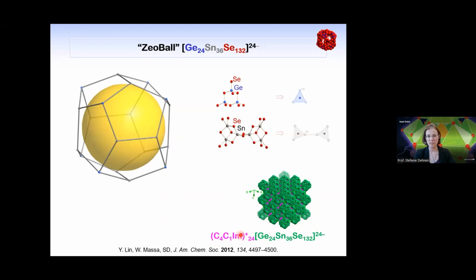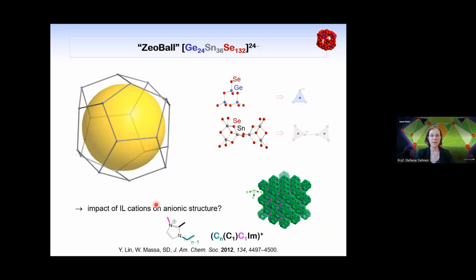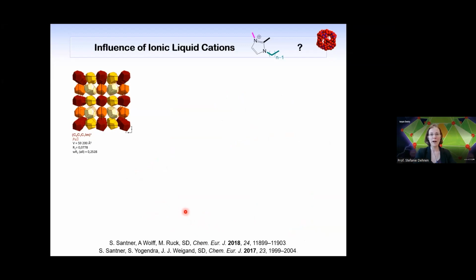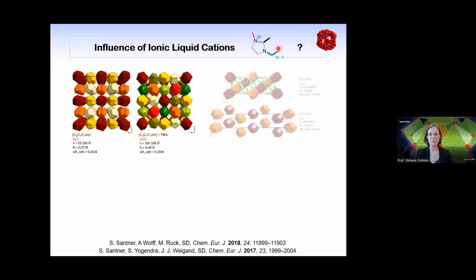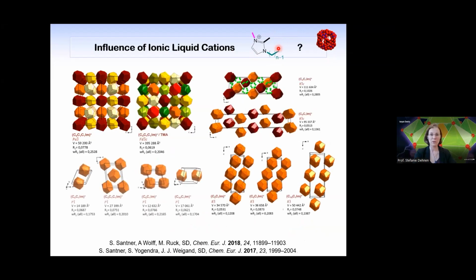Well, getting back to the structure, we recognize, and I also said, that these counter ions played a role in this structure. And the question was, can we have an impact when changing and exchanging these cations? So we played with these imidazolium-based counter ions, and this is what we do. We replace this alkyl group here. This group can be replaced easily by just normal organic syntheses. And we tried a couple of different alkyl-based imidazolium counter ions in our ionic liquids. And this is the result of some of these experiments, which told us that we always have the same anion.